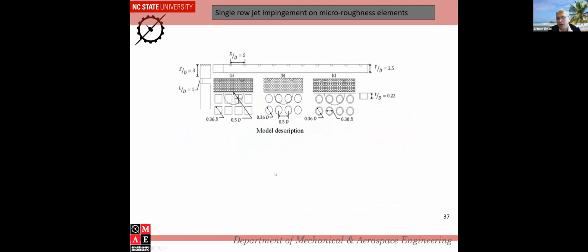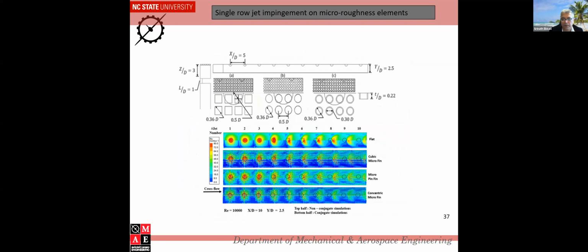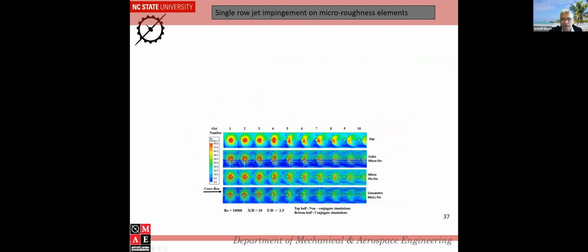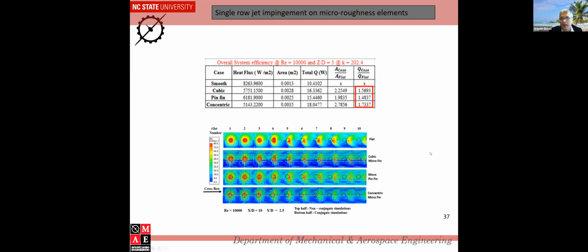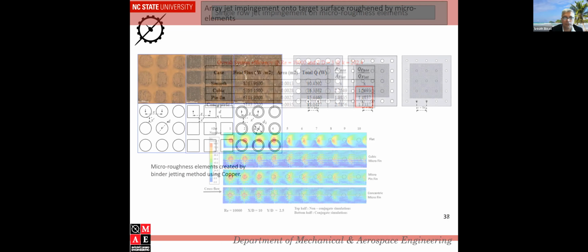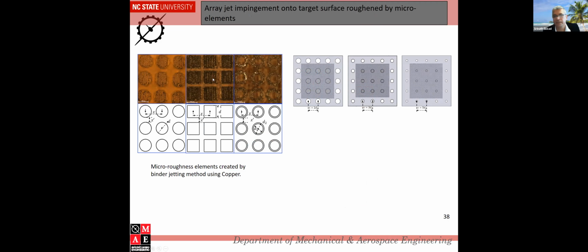And then we are also doing some impingement cooling with different kinds of 3D printed surfaces. These are micro pin fins with cubic, micro, and concentric micro fins, and you can see micro fins can enhance heat transfer quite a bit. And we can get up to 73% higher heat flux than traditional flat surface impingement. So this is 3D printed surfaces as you were watching. This is our micro roughness. This is a circular pin fin.